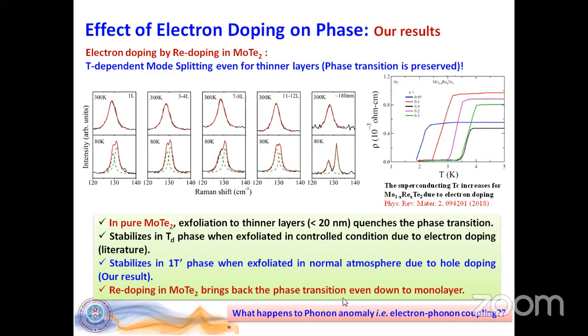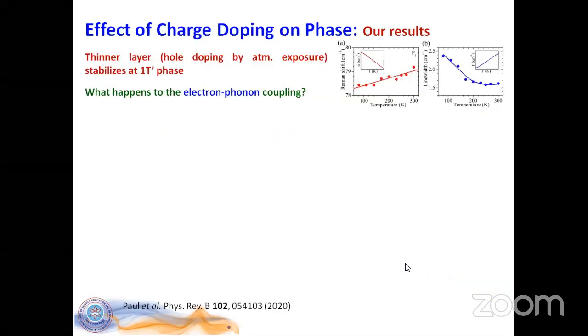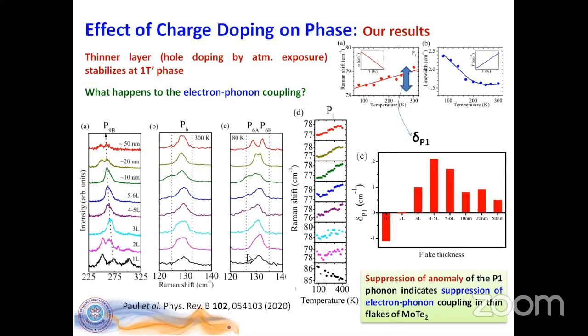Now let's quickly look at what happens with the phonon anomaly, or the electron-phonon coupling that we touched upon. Just to remind, the change in the phonon tells us about it. Here we show at different layers how the trend changes. Here is the very thick layer, and then as we thin down, down to the monolayer. This is for pure MoTe2, not the doped one. In the pure MoTe2, in the thin layer sample we see a reversal of the behavior.